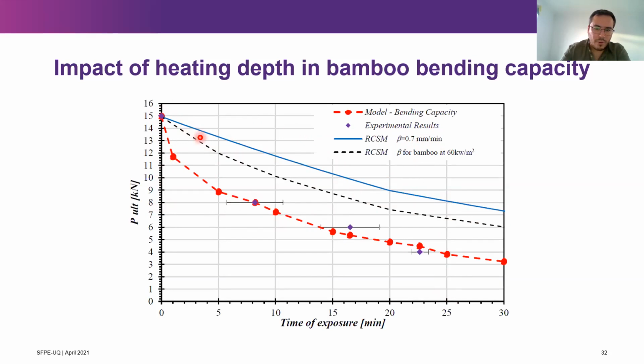And again, we also tried to apply the reduced cross-section method, but instead of using a conventional charring rate, we use the results of our experimental test for 60 kilowatts per square meter. And even though we had very accurate charring rates, which in some cases, if I remember well, were up to 1.3 millimeters per minute, you still overpredict the fire resistance of bamboo. So obviously, our model is way closer to reality, and this allows us to get way better results.